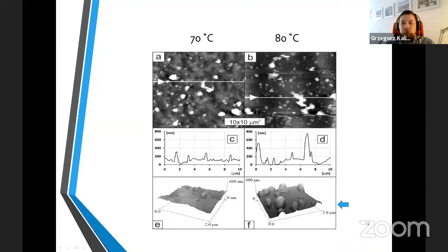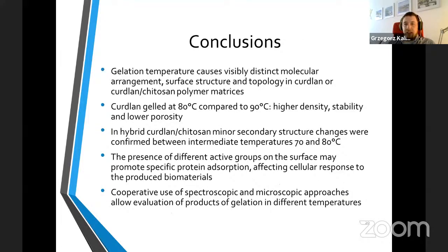Depending on what we want from our designed product. So to conclude, curdlan gelation temperature affects distinctly molecular arrangement, surface structure, and topology of the polymer, which can be modified in production regarding application. And it goes with solely curdlan or even hybrids made of curdlan and chitosan. At 80 degrees, compared to 90 degrees, it has higher density, higher stability, and lower porosity.